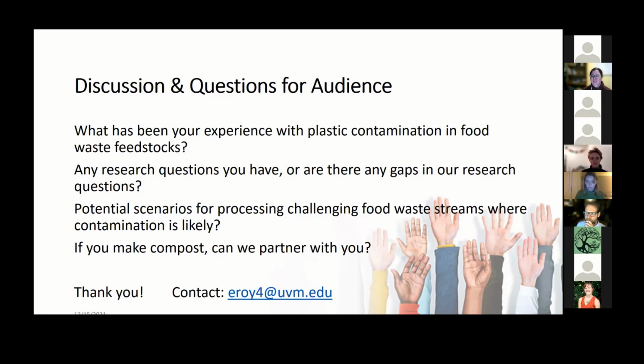Yeah, for sure. Sarah, I see you unmuted. Did you want to add something? Yeah, I was just going to reiterate that we don't have standard methods for counting microplastics. A lot of these industries and private research, those methods aren't really shared, and it's not very likely that they'll have access to the same instrumentation to measure microplastics. Or, what size are we even considering for microplastic? You'll get way higher counts if you're considering down to like 20 micrometers. So yeah, it's just so context dependent.